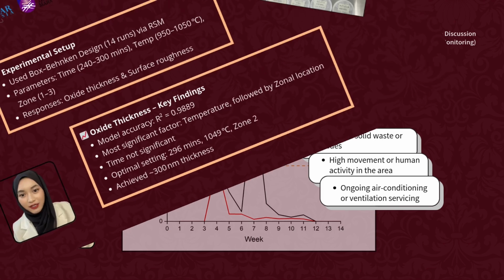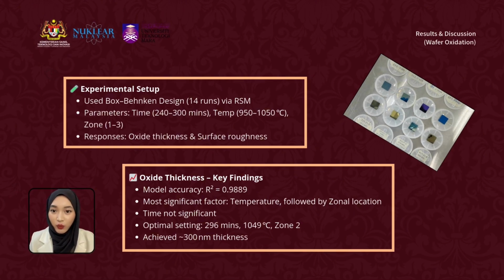For the oxidation study, we used a Box-Behnken design with 14 experimental runs. The three process parameters were oxidation time, temperature, and furnace zone. The responses studied were oxide thickness and surface roughness. The regression model for oxide thickness has an R-squared value of 0.9889, which equals 99%, indicating a high accuracy.